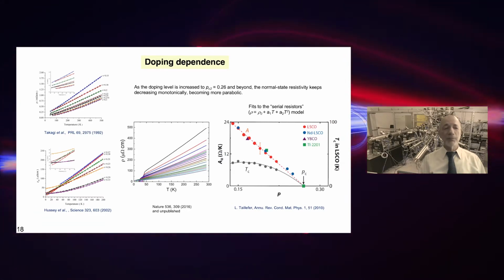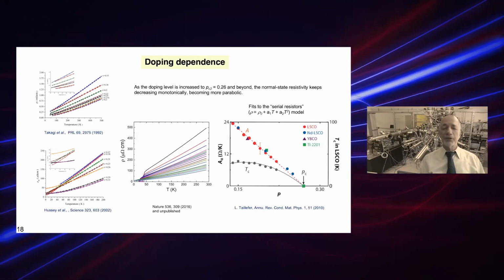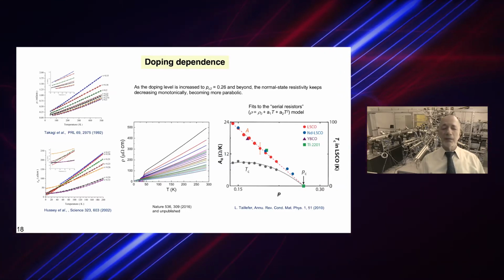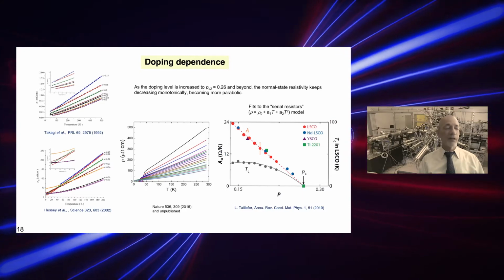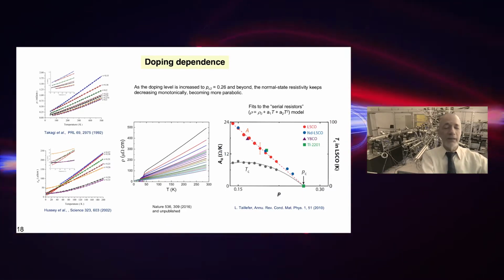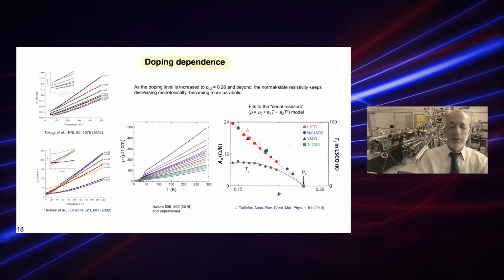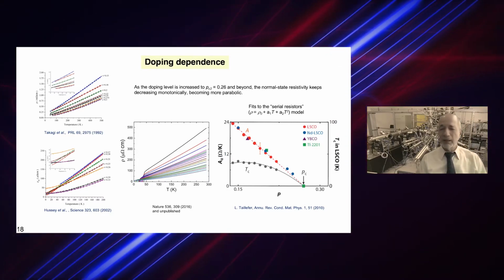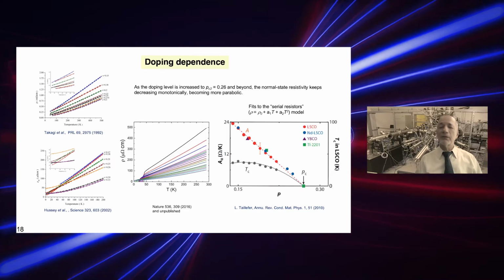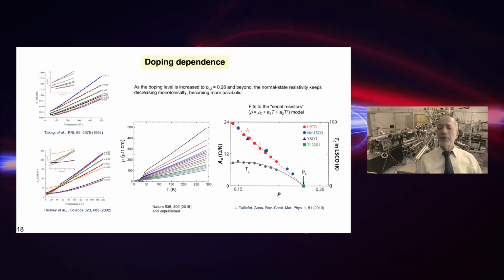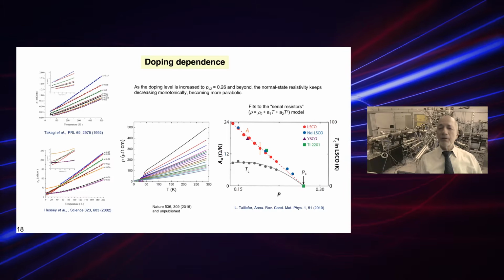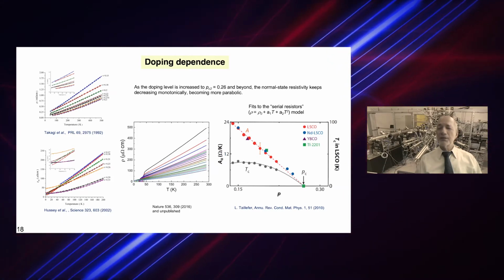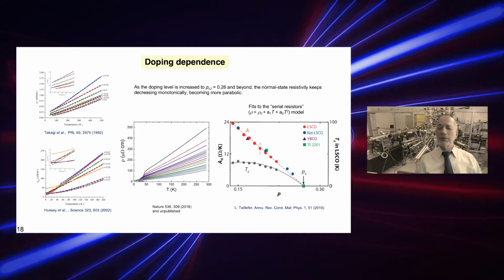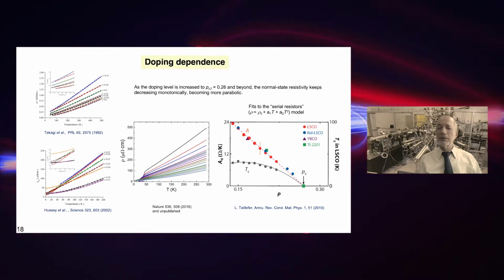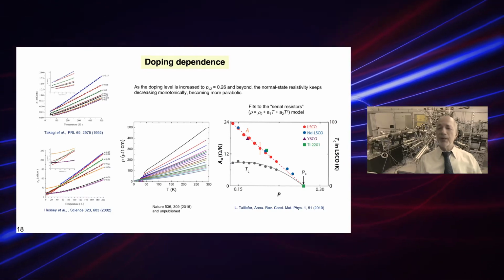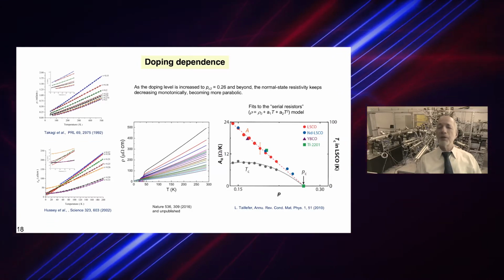At low temperature and high doping, there is more of a parabolic curvature. In the middle are some very recent systematic data that we collected on well over 1,000 devices and doping levels. To the right is the result of fitting to the serial resistor model. Rho equals rho naught, the residual resistivity, plus a term linear in temperature, plus a parabolic term.